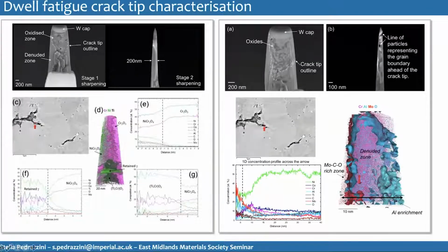And then I picked up a few more samples out of that cantilever that I made before. So the first one was a bit more central down here, and then the second one I tried to pick up the crack tip, like the point where the oxide sort of goes in, it becomes grain boundary ahead of the crack right here. And I was able to pick that up. I didn't get a lot of data out of it, but enough to know that this is the oxide. We can see it in the needle, and I sharpened it until I started seeing some of the darker particles at the grain boundary ahead, because I wanted to figure out what they were.